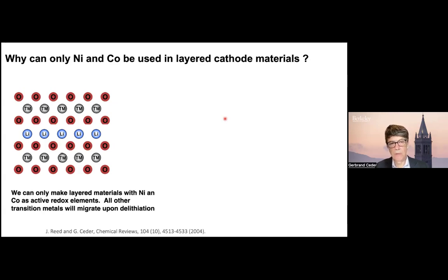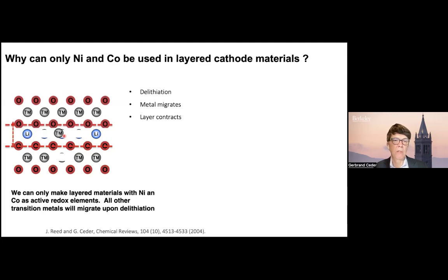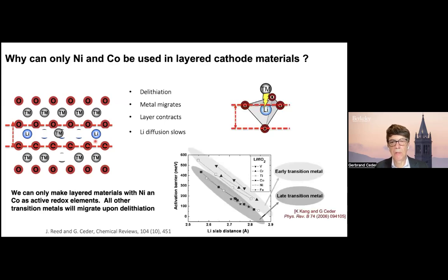And that's been known for now over 20 years, but it's useful to remind ourselves that there's a reason it's called the NMC class, and the only redox active materials in the NMC class are nickel and cobalt, and that has to do with their mobility in close-packed oxides. So if you take a layered material, and I have sort of a cartoon here, and you pull lithium out, what actually happens if you go over about half lithium extraction is that metals start to migrate into the lithium space. And because of their higher valence state, they actually contract the oxygen layers around them. And because of that contraction, the lithium mobility goes down.